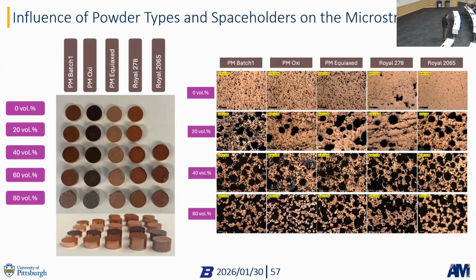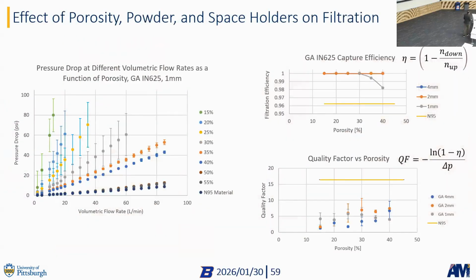We also added space holders to our materials, to add extra space, extra porosity. And then we looked at how the amount of space holders affects the microstructure for each of these different powders that we got. So you see, we got a large variety of microstructures, right? And that will result in a large variety of pressure drops, of capture efficiency, so how many particles are actually getting captured, and then the quality of these filters. And we are right now testing all of these. So these are the first results.